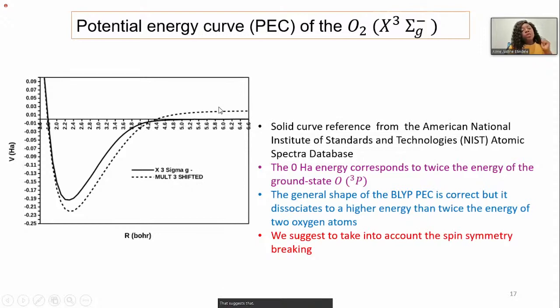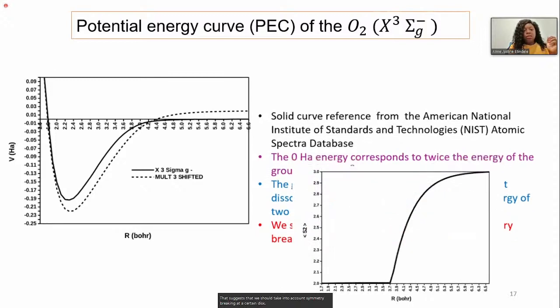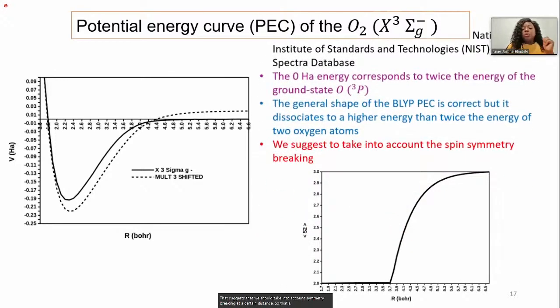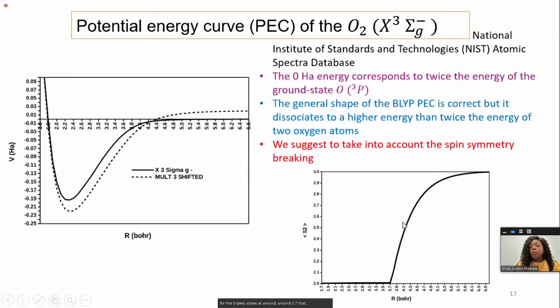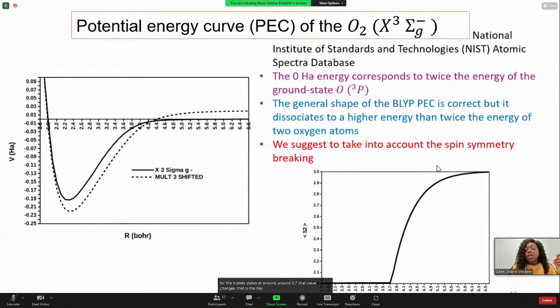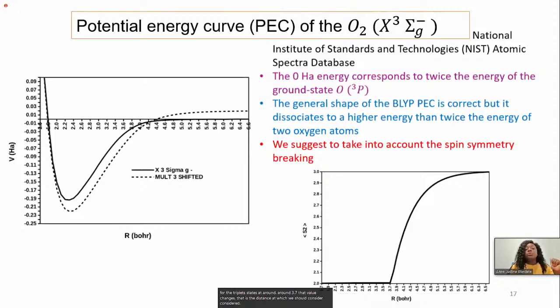That suggests that we should take into account the symmetry breaking at a certain distance. That symmetry breaking is basically attributed to the change in the value of the expectation value of the S square operator. That is supposed to be equal to 2 for the triplet state; at around 3.7 that value changes, and that is the distance at which we should consider the symmetry breaking.